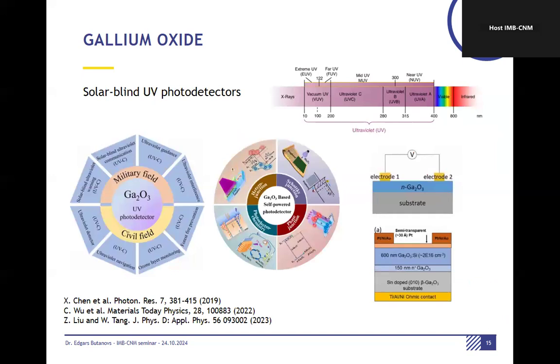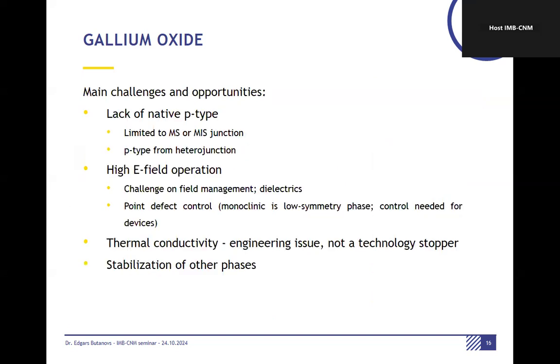Another thing I'm interested in is solar blind UV detectors. Since we have quite a wide band gap, we can start detection in the range around 200 to 240 nanometer wavelength. The competitor there is AlGaN, but it's still a kind of expensive technology, and I think it has a bit smaller band gap. And here, I think with AlGaO, alloying gallium oxide with aluminum, we could obtain very nice UVC detectors.